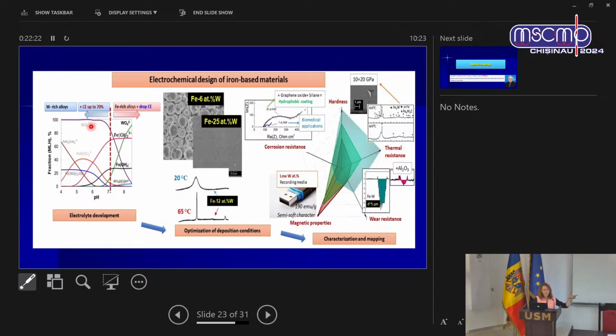And you can obtain, for example, tungsten-rich or iron-tungsten-rich alloys. And why it's important: you can obtain different morphology, different structure for the same amount of tungsten by only switching temperature. And if we map all these characteristics which were studied, like hardness, thermal resistance, and so on, of course tungsten-rich alloys have high hardness and also high thermal resistance. For example, you see 10, 20 gigapascal, depending on the heat treatment, which is a nice result and also applicable for thermal application.